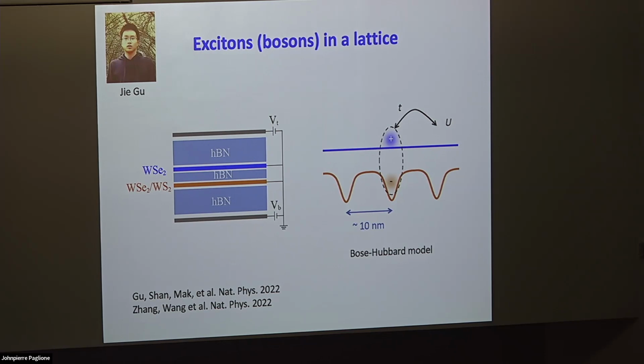And for graphene, of course, there are some practical advantages, especially when you're doing transport measurements. You don't have much of a problem forming good contacts on this material, whereas we struggle a lot with contacts in TMDs. So graphene is nice; you can easily do electrical measurements on it. But on the other hand, you cannot really do optical measurements on graphene. There's no feature and things like that. So they're totally different, and I think both are interesting. They just provide different paradigms for studying correlation physics.